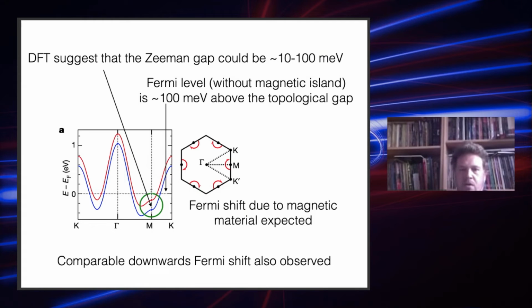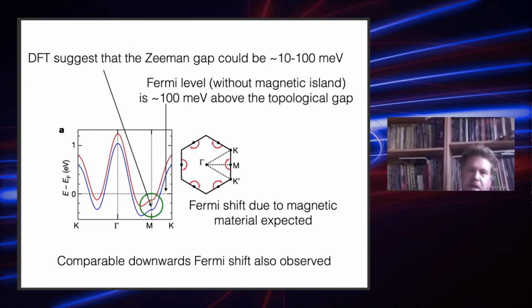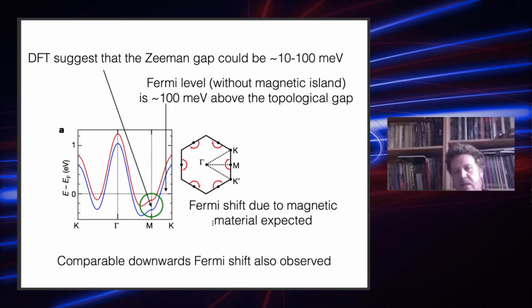So somehow we would need this pristine Fermi energy to shift down here. And it doesn't really require that much fine-tuning, because this topological gap is then sizable. So if we have a little bit of downward shift of the Fermi level, then we are in the topological gap, and our system is tentatively a chiral superconductor with Chern number C.